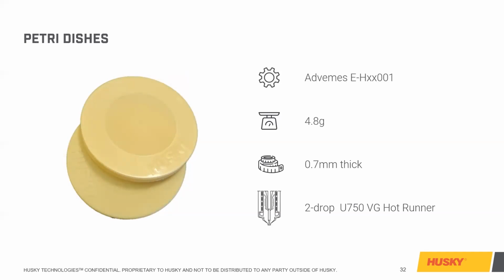So the core on this mold is adjustable, which allows us to change the wall thickness, which in turn changes the part weight to try and mimic the specific application that the customer is trying to run. So again, these are resin trials that we did with a Husky tool to confirm that the resin is processable, to learn as much as we can before we design the production system.